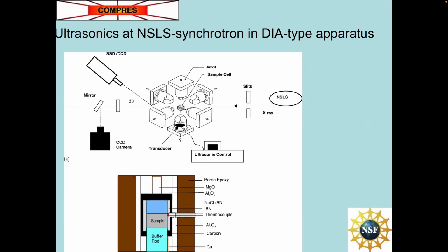So you can't blow this up very well, but the signal comes in from the anvil through a buffer rod into the sample and reflects at every interface, including the one with sodium chloride. The sodium chloride and boron nitride are used to create a pseudo-hydrostatic pressure environment around the sample, which we think is pretty important. Next slide.